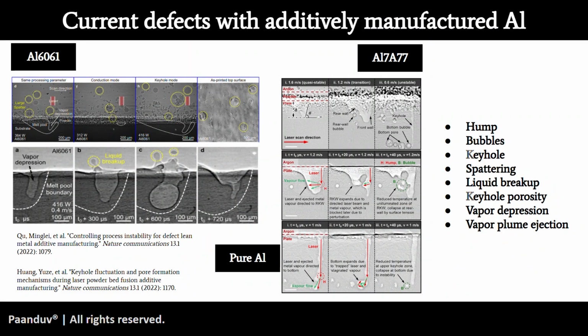When we talk about defects in additive manufacturing, irrespective of whether it's an aluminium alloy or some other alloy, we typically encounter the same sort of defects. They can be more pronounced in the case of aluminium, but the defects remain nevertheless. For example, we can talk about keyholes, which is one of the most scary defects that all 3D printer users want to avoid: spattering, liquid breakup, extreme porosities, whether due to keyhole or even in the other modes of heating, vapor depression, vapor plume ejection, humps that reduce the surface finish of your part, and many other defects that we encounter on a regular basis.